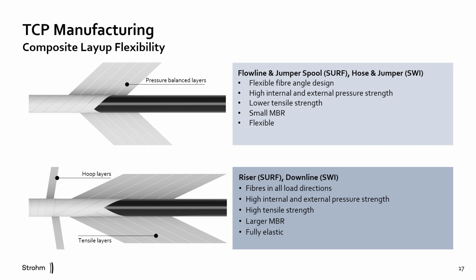In its simplest form, we split this into two main categories, which we call our flowline layup and our riser layup. Generally, the flowline layup is for the static or quasi-static applications that do not require an enhanced tensile performance. In these designs, the tape angle that we use gives us a balance between the internal pressure resistance, the external pressure resistance, and the tensile capacity of the pipe. As this name suggests, this is an ideal layup for flow lines and is also used for jumpers.